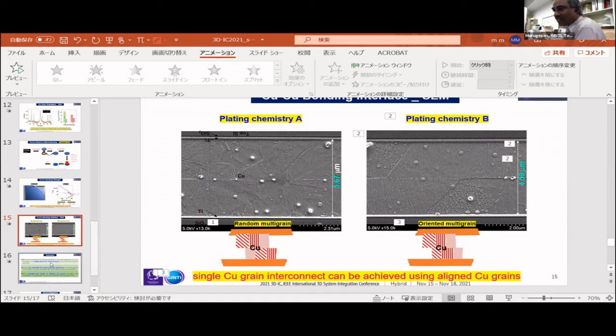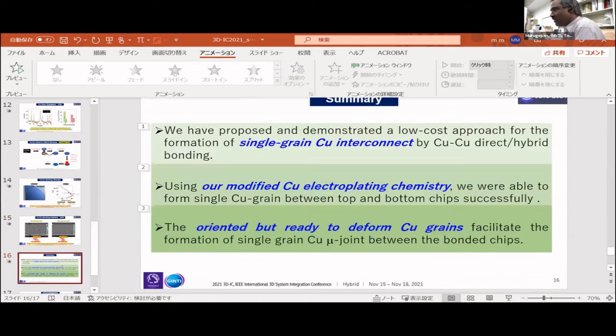So with this, I would like to conclude my talk. We have proposed how to form single grain copper interconnect. Based on our modified electroplating chemistry, we were able to form nice single grain copper between the top and bottom die. Our results show that our grains are really oriented, and also the low hardness value helps to form a very nice single joint between the top and bottom die.